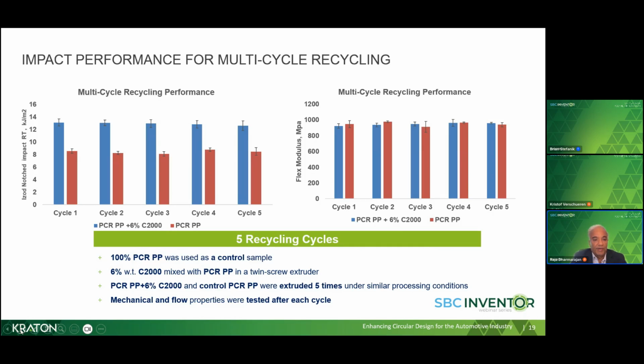The first one is our standard PCR-PP, and the second one is a PCR-PP that contains 6% of our Circular Plus C2000 grade. So at the end of each cycle, we injection molded test specimens and measured performance: Izod, stiffness, and flow. And as you can see here, with 5 cycles, we don't see any of the properties being diminished. We are able to maintain both impact and stiffness up to 5 cycles, as you can see in this graph.